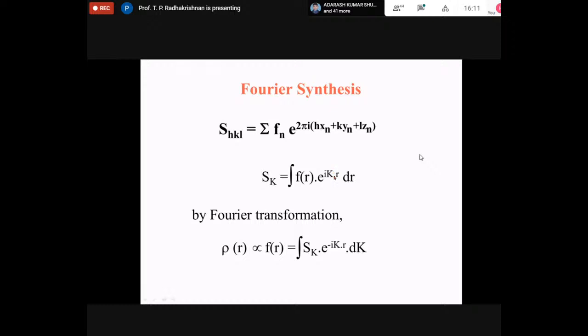And this phase factor is represented by this product, which is basically a vector product of a real lattice vector, which relates to lattice points in a real crystal, and k, what is technically called a reciprocal lattice vector. Let us not worry about it. So the so-called Fourier transformation converts an integral like this, if S(k) is an integral of this function in this space, by Fourier transformation, I can transform space. For example, I can write this function F(r) in terms of S(k) e to the power minus ik·r dk. So I am integrating here in real space. Here it is integrated in reciprocal space.